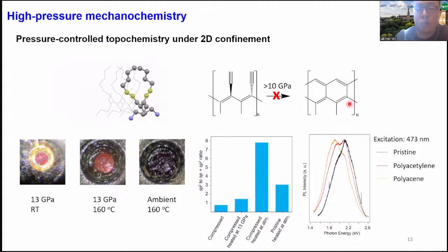You have to pay a very large energy penalty for these two triple bonds to rotate into the same plane. In other words, pressure in this case is limiting the accessible conformational space of our intermediate product, and therefore preventing the reaction of the second step.